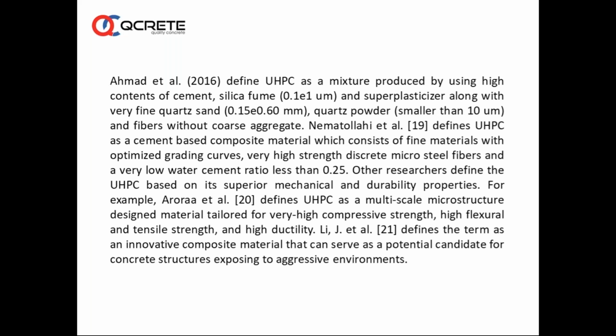So you can see different people defining it in their own way actually. For example, Aurora defines UHPC as a multi-scale microstructure designed material tailored for very high compressive strength, high flexural and tensile strength, and high ductility. Another defines the term as an innovative composite material that can serve as a potential candidate for concrete structures exposed to aggressive environment. This is the most important point actually. The resistance to chemicals, resistance to aggressive environment is enhanced significantly when we are talking about UHPC. The durability also is improved proportionately.